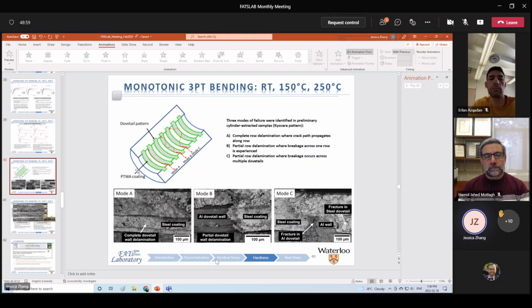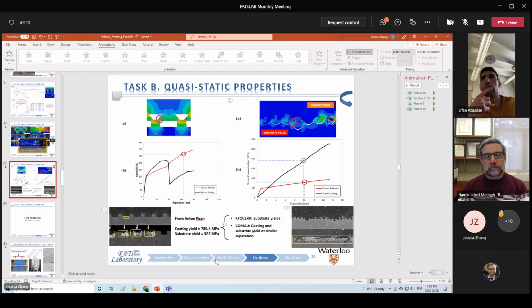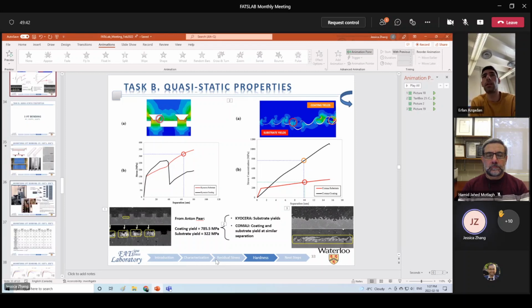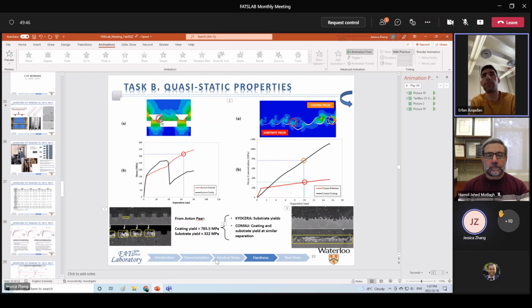One thing that we did notice in our initial tests was that there was a lot of breakage at the interface, specifically at these horizontal sidewalls, and we were really interested in seeing why that was. And when I think Dalal actually looked at it using SEM, he saw a huge layer of resolidified particles that we weren't able to see because we were previously viewing it at this angle, just right there. So it really affected the amount of effective bonding that we can get in this pattern. So I guess that would be the main difference between the two patterns. The failure path, not so much, but the reason why it initiates here at the interface.